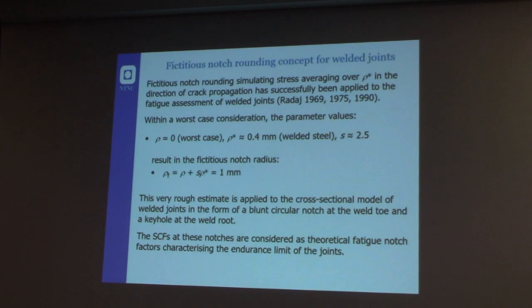Radaj proposed this in the standard for weldments and welded joints. For welded joints, the equation is rho f equal to rho plus S times rho star, where rho is equal to 0 as the worst case condition, S is equal to 2.5, and rho star is equal to 0.4. So for design purposes, what they are doing is giving a fictitious notch radius of 1 millimeter. If you want to design a weldment, you have to substitute the real value at the weld toe with this notch radius, and you can directly read the stress field or the stress concentration factor at the notch with a radius equal to 1 millimeter.